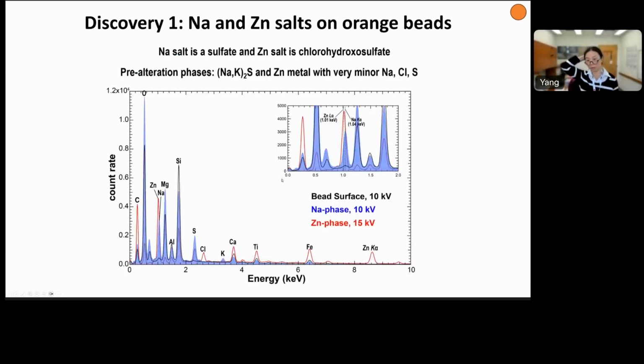When we look at the chemistry of those two phases with SEM EDS, of course, we tried different voltages in order to confirm the zinc is present in that bright phase. So we used SEM EDS to constrain the chemistry, because although those are bigger, micron-sized grains, they are very thin. So we used different excitation energies to minimize the contamination from the substrate underlying the phases.